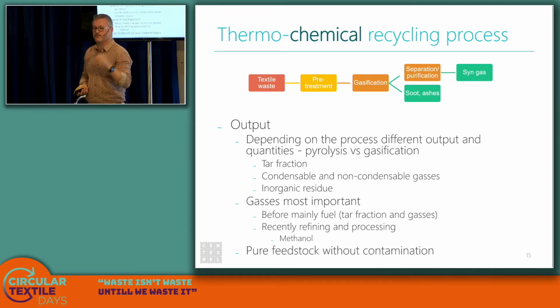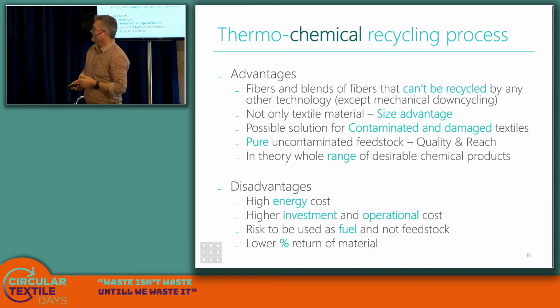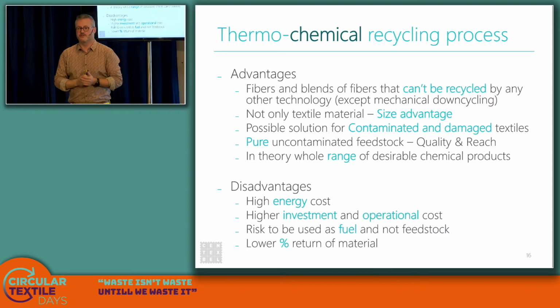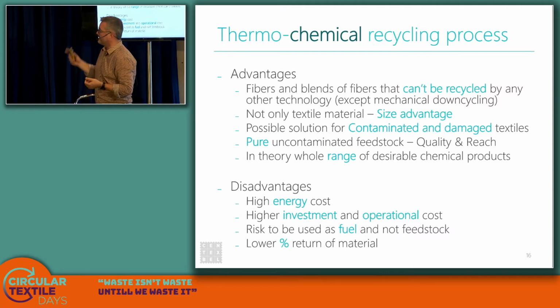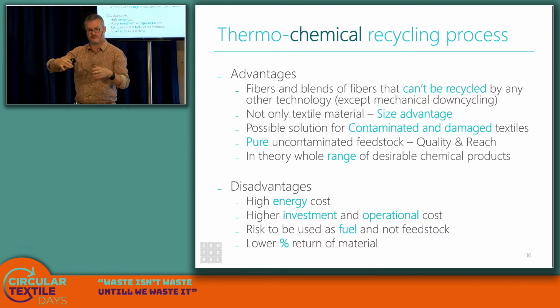And here, your feedstock is pure. You don't have contaminations. So REACH regulation is not an issue. The advantage is probably that in the future you will have a technology to recycle fibers that are in quantities very little in use, like aramid fibers. The quantities are very low, so perhaps this will be a technology that you can recycle aramid fibers, for instance. There's a size advantage because you can also blend in plastic materials from other industries. So the textile is blended in with other materials. You have a pure feedstock, and you have a range of chemical products. So depending on what you are doing within your process, you can have another outcome for another industry to be used.